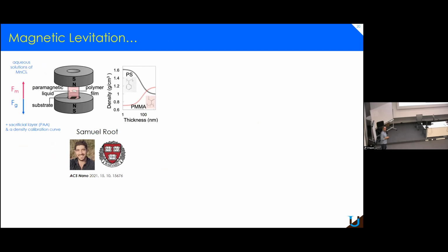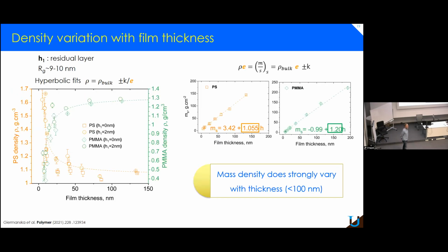Jean-Paul: I'm sorry, maybe I missed something, but you control the thickness by changing the time of contact with polymer? Well, actually, no, we are not controlling the thickness, but we are spin coating the film. We are measuring the thickness of the spin coated film. So we have the thickness of the film. We put it in the QCM with toluene. Toluene dissolves everything. Okay, so you control the thickness at the beginning. At the beginning, yeah, obviously, otherwise you cannot access it. And you measure it? We are measuring with ellipsometry, X-ray, and AFM to triple check, I would say. And at the end, it's what we got.